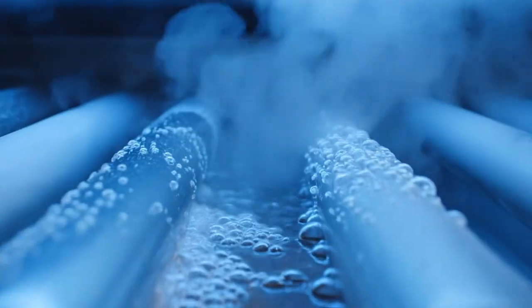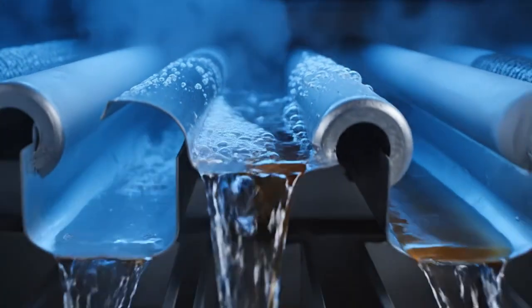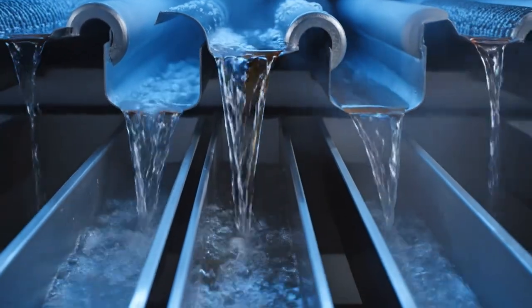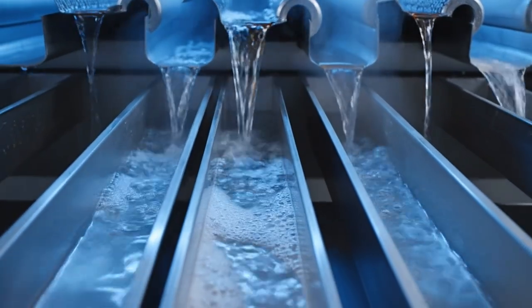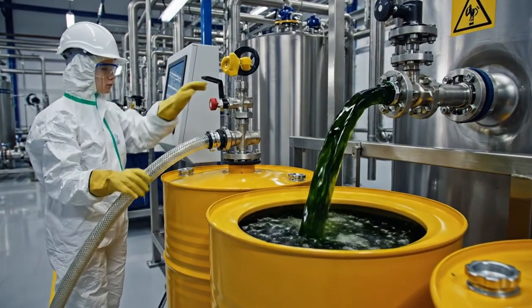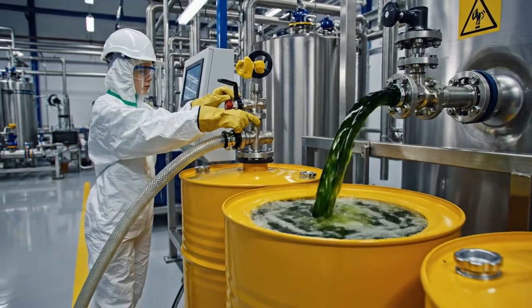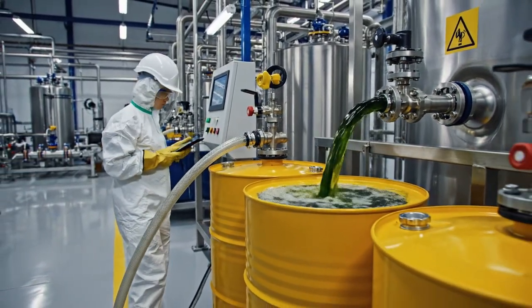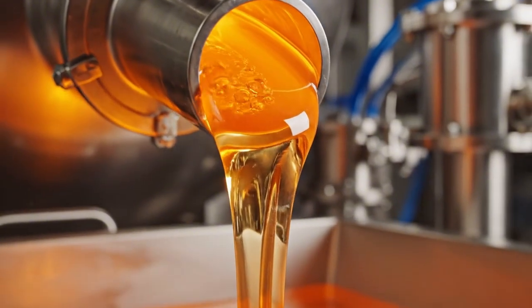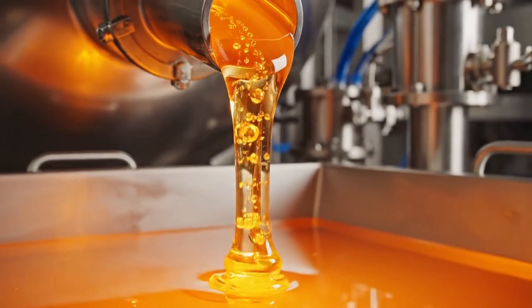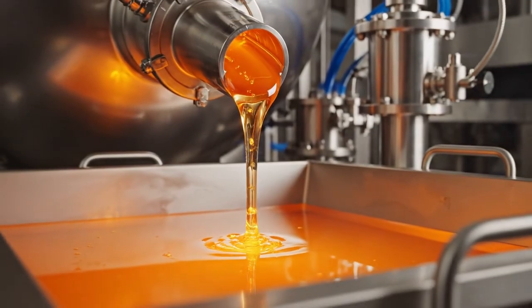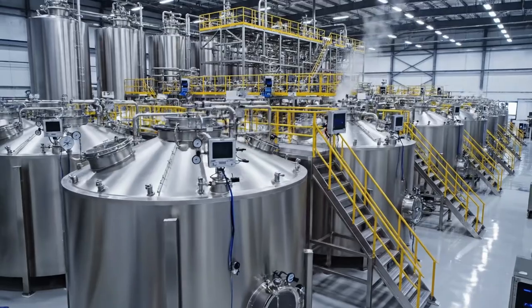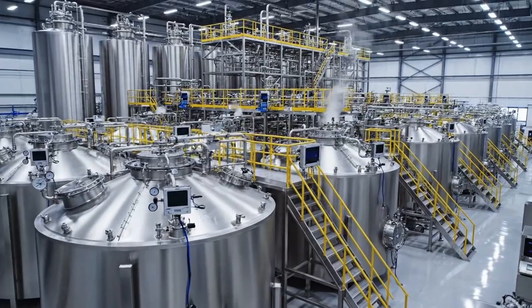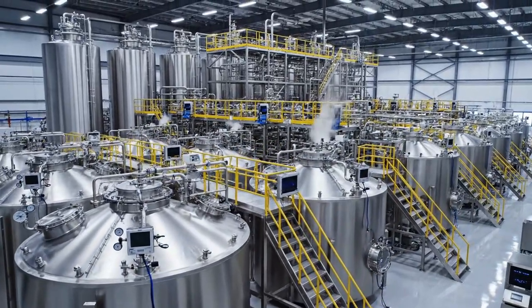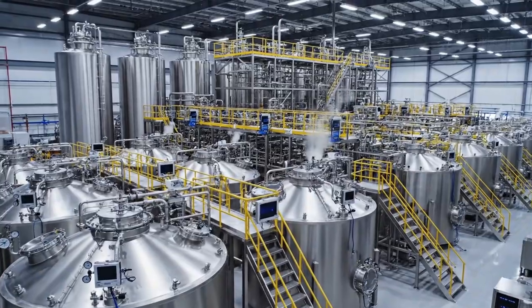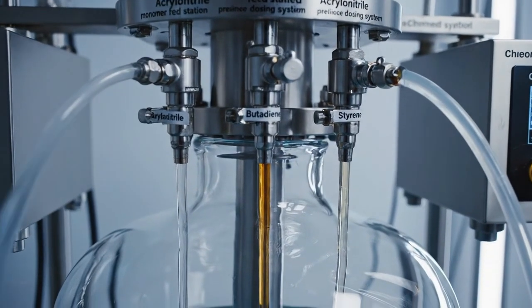Vacuum distillation. Pumps reduce the reactor's internal pressure to near vacuum, causing volatile compounds to vaporize and separate from the polymer matrix. The vapors are captured in condensation towers where they cool and liquefy, becoming industrial waste streams destined for specialized disposal. What remains in the reactor is purified ABS resin, stripped of contaminants, and ready for the most critical transformation of all. Repolymerization is where chemistry transcends engineering and becomes almost biological.